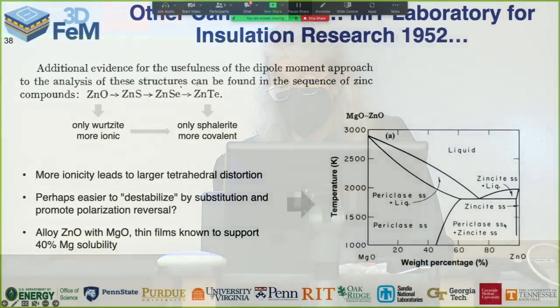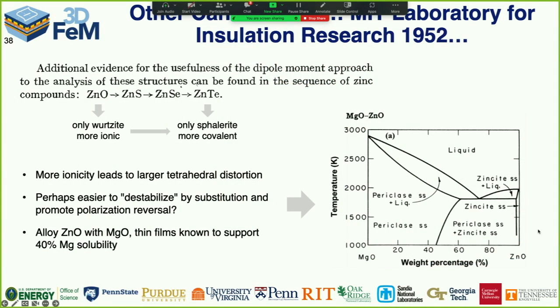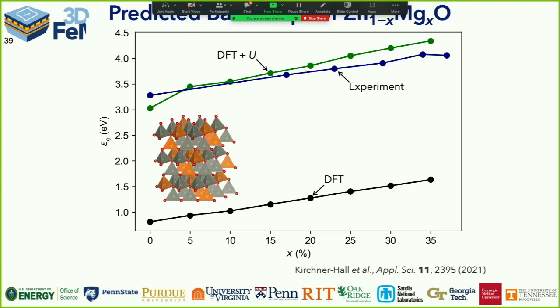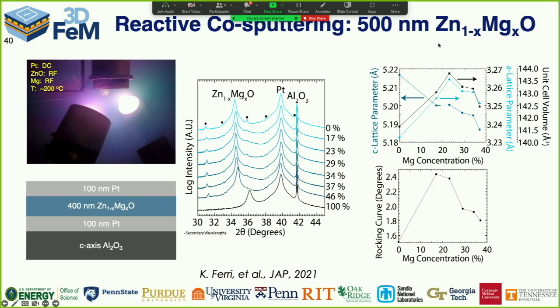There's actually thermodynamic stability says I don't have much room to put much magnesium in, but there is an enormous literature on this that says in thin films you can get about 40% magnesium into this structure. And here, the band gap actually goes up when I add magnesium into zinc oxide, so very helpful. Use the same trick. We use reactive magnetron sputtering. Again, work from John Paul Maria's group.